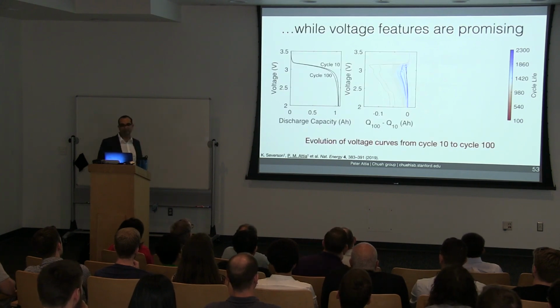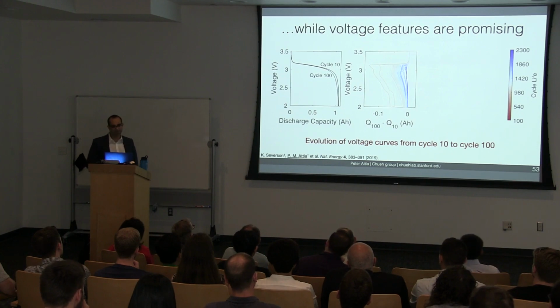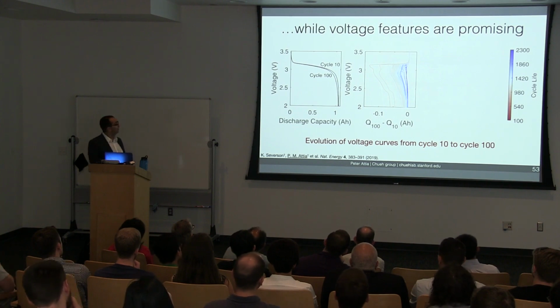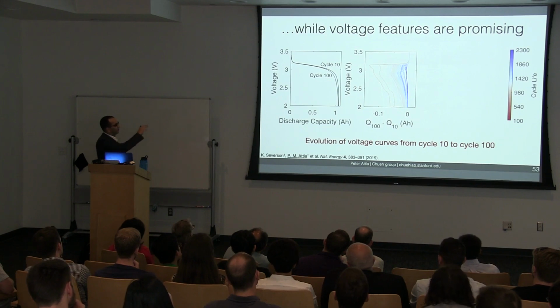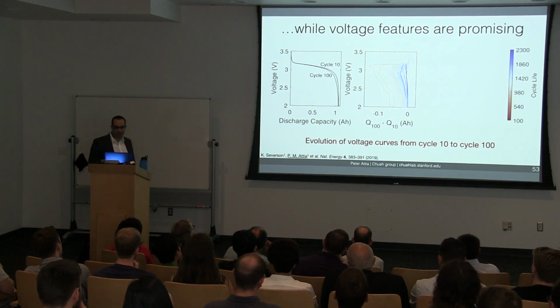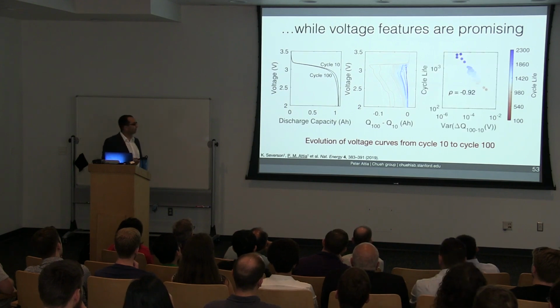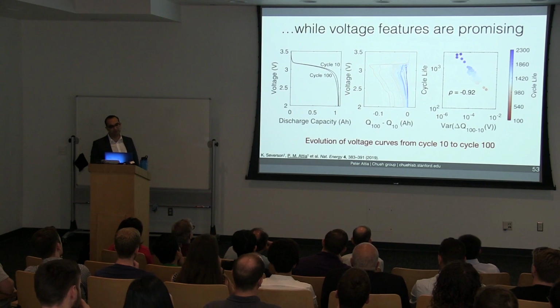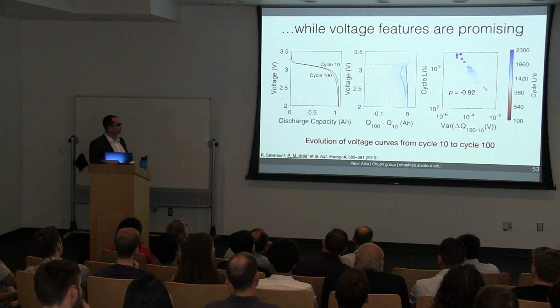This was initially a pretty discouraging result because it suggested that early cycle prediction was not possible. However, if we build features based on the voltage curves, we get features that are much more predictive. This feature here is basically looking at the evolution of voltage curves from cycle 10 to cycle 100. And here we immediately see a clear trend in color. The red curves show a big change from cycle 10 to cycle 100, which suggests that the cycle life is low. And the blue curves show a small change, which has correspondingly high cycle life. If we convert these vectors into scalars using the variance function, we find that this feature strongly correlates with cycle life. Now, one thing to note is that this voltage data is relatively messy, which is why a lot of people don't use it. They throw it away. But it seems to be the most important for early prediction.